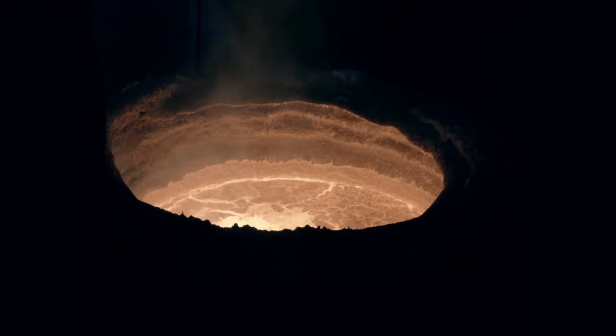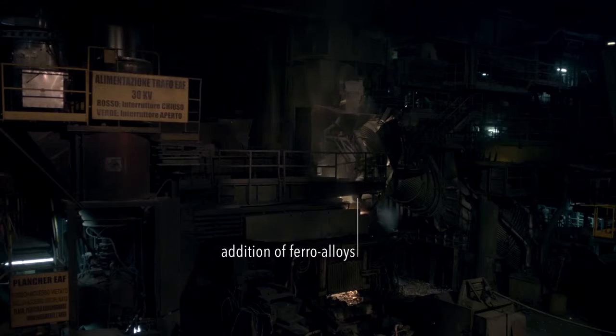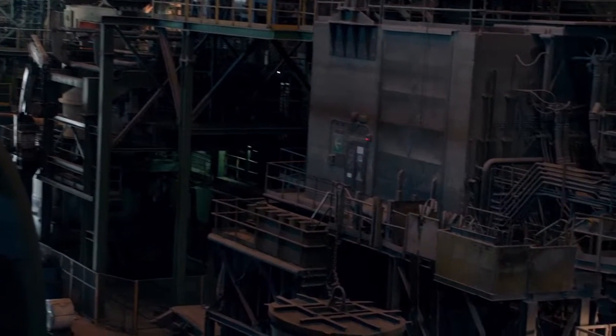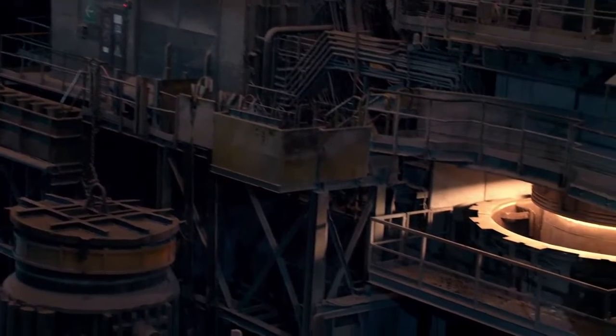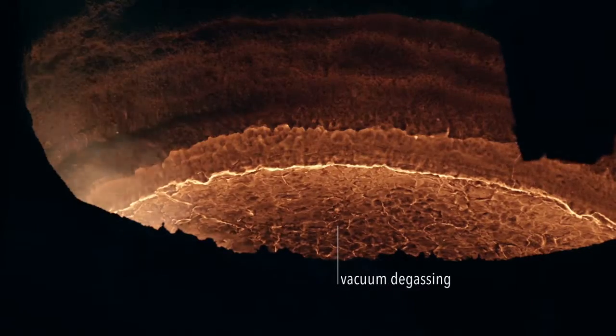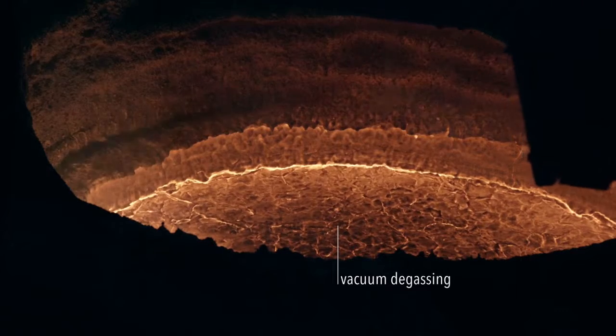Liquid steel is refined in the furnace by argon bubbling. Ferroalloys are added to achieve the ideal chemical composition. Temperature is carefully controlled to allow the best casting conditions. At this stage, vacuum degassing for special steels is performed.